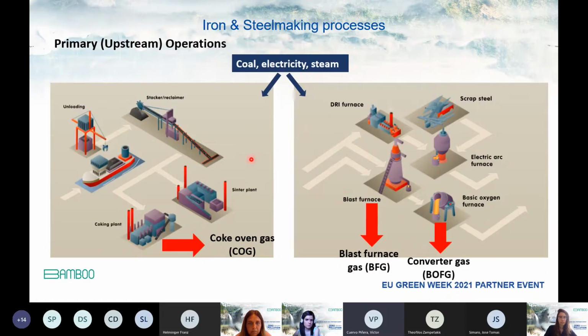So in detail, if we take a look at the primary operations that we presented before, in the coke plants, we take the coal and we generate the coke, that is the raw material for the blast furnace, and as a byproduct we produce what we call coke oven gas. The heating value of this coke oven gas is more or less half of the heating value of natural gas. It's very rich in hydrogen, and we try to use this gas within our processes as much as possible.